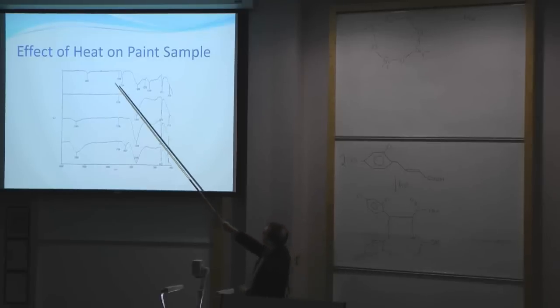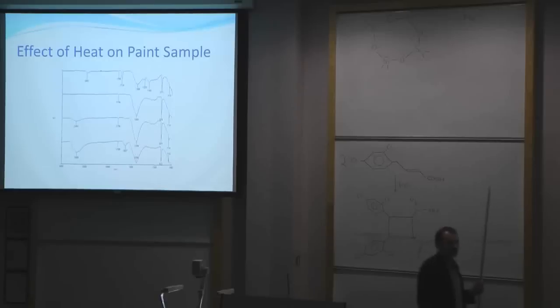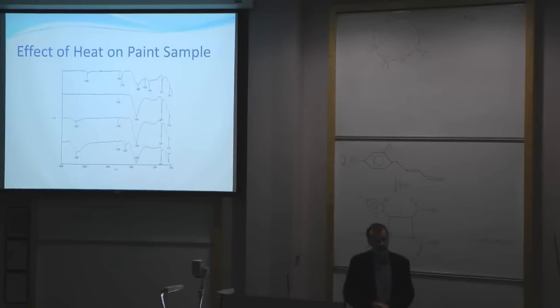There's a nice carbonyl peak up here that disappears quite clearly at an early temperature. A really interesting thing, if you go down to these peaks at the bottom, you start to see a water peak appearing when you get to high temperature. I couldn't understand that at first, but then I realised what is happening is that you're degrading the paint sample so that when it cools down, it becomes more hygroscopic and takes up water. And the appearance of this water peak actually seemed quite definitive of something that had been heated to a high temperature and then cooled again. And not quite what I expected.